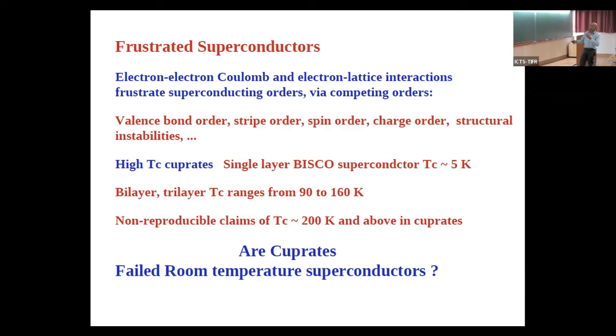So what do I mean by frustrated superconductors? If you take a superconductor, electron-electron Coulomb repulsion and electron-lattice interactions frustrate superconducting order. For example, in cuprates, you very often see in the underdoped regime, in various experimental measurements, valence bond order, stripe order, spin order, charge order, and structural instabilities.